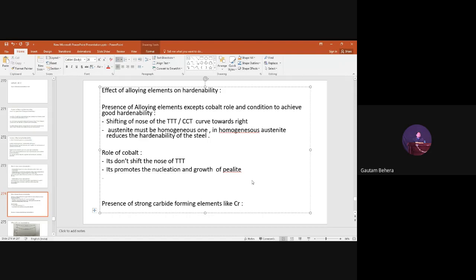So you understand, what can I write? Martensite transformation is suppressed, because pearlite formation will be there, so martensite transformation will be suppressed. If you have a steel containing only cobalt, it will never shift the nose of the TTT curve towards the right, right? So we cannot easily get martensite upon slow cooling.